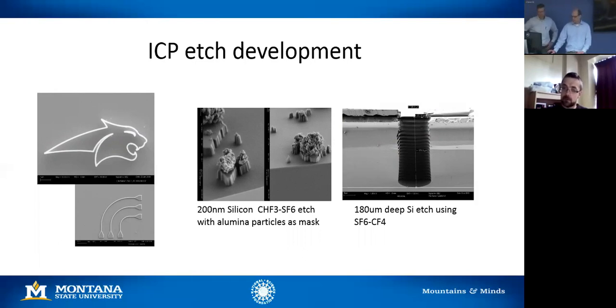There are some examples. Here's an MSU Bobcat that's probably around 100 nanometers, given what I can remember from it. Another one here is little waveguides, light guides for, I'm guessing, an infrared application. And this one I like because this is just grit. It's aluminum oxide from a polishing solution, a polishing slurry, dried on the wafer, put in, and we used the Si etch process. It's actually a 180 micron deep etch.